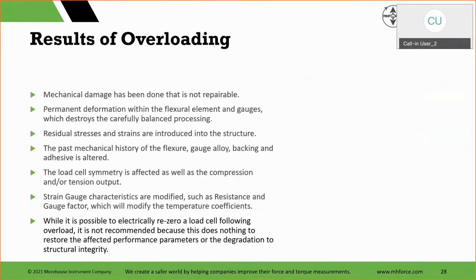Results of overloading. We get asked a lot, hey, can it be repaired? Typically the answer is no. Mechanical damage has been done that is not repairable. Permanent deformation within the flexural element and gauges, which destroys the carefully balanced processing. It's done. You have material that no one really knows how much it's been deformed, right? The residual stresses and strains are introduced into the structure. So going back and saying, hey, you can't calculate a lot of this. So re-gauging it is painful. More often than not, you can't get it right.